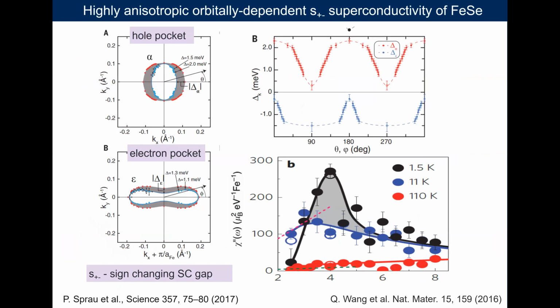Well, I think this is one of the potential evidence for that. And there's been some other neutron diffraction too. Is that powder data? It could be lots of hundreds of single crystals, I think. Is that Q vector going out along the x-axis, momentum? So here I haven't checked the exact values, it's energy, but it's been suggested that the development of this peak in neutron diffraction seems to be equivalent to the nesting vector between the electron and hole pockets. Ah, I see. It seems to have the right Q vector.